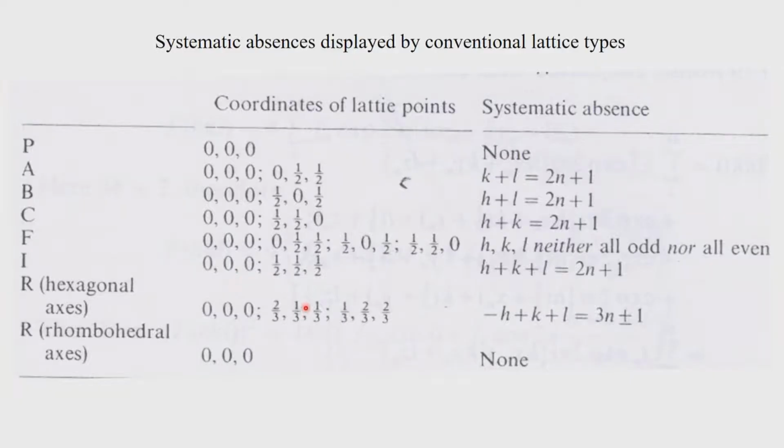If we have a rhombohedral cell and fix it in a hexagonal lattice, then we have this problem, and this problem is because the rhombohedral axis now will show coordinates of these 3 positions, and that is the property of the rhombohedral cell. It is a special case of the hexagonal lattice. All hexagonal lattices will not show. So, in principle if we have a hexagonal system which is indexed as a hexagonal system, you have a equals b not equal to c, alpha beta 90 degrees, gamma 120, and then it shows rhombohedral symmetry, then you will have these systematic absences. So, this is very interesting.